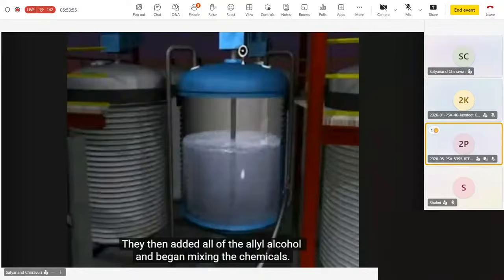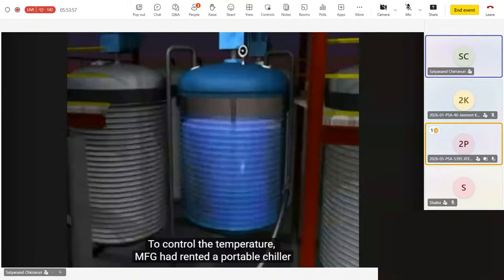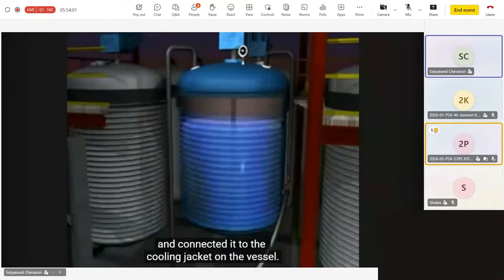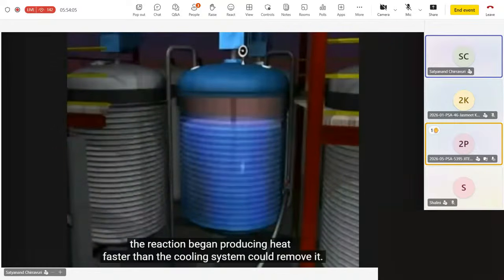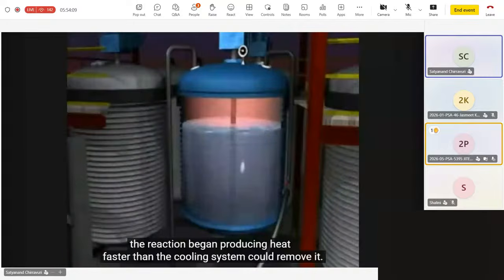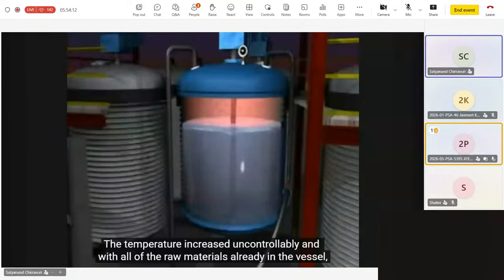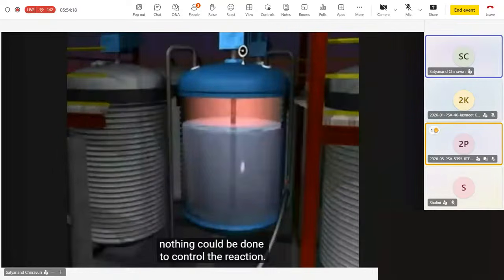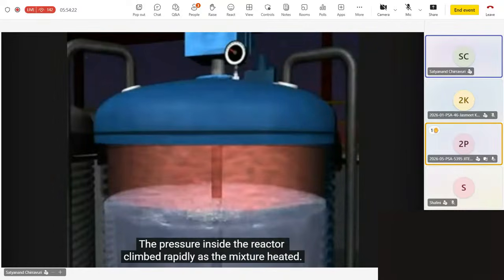To control the temperature, MFG had rented a portable chiller and connected it to the cooling jacket on the vessel. But as soon as all of the raw materials were combined, the reaction began producing heat faster than the cooling system could remove it. The temperature increased uncontrollably, and with all of the raw materials already in the vessel, nothing could be done to control the reaction. The pressure inside the reactor climbed rapidly as the mixture heated.